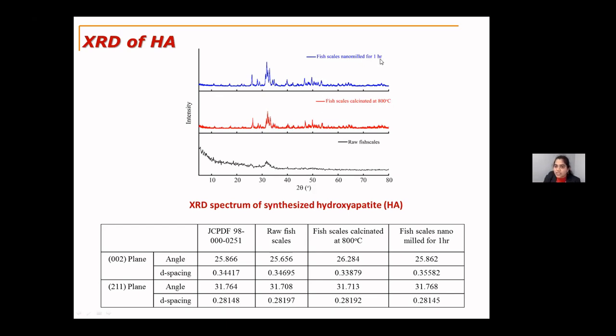And when it is nanomilled for 1 hour, this was more clear and more intensive. The peaks were more clear. And I chose to show two planes here. I recorded two plane angles and the d-spacing here. So the JCPDF file is the available commercial hydroxyapatite, the standard one, which is available for the XRD. The angle is at around 25.866, and the peak for the nanomilled fish scale was found at 25.862, which is very close. Also, the d-spacing is almost similar. It's 0.34 and it's around 0.35.